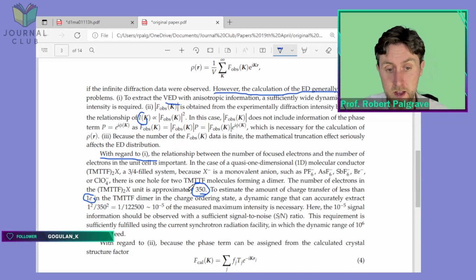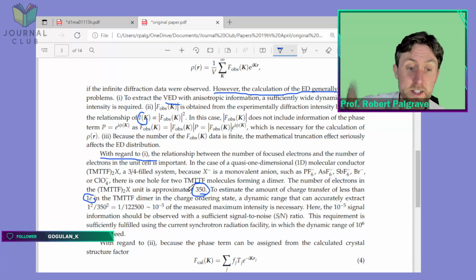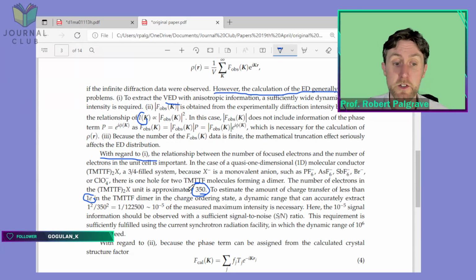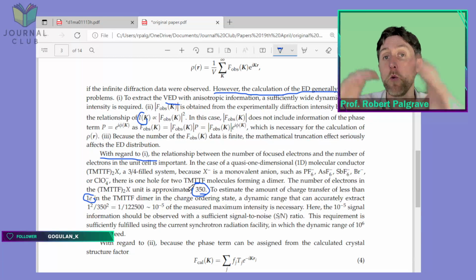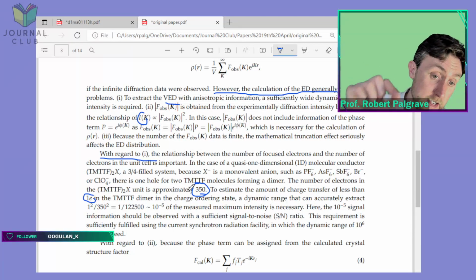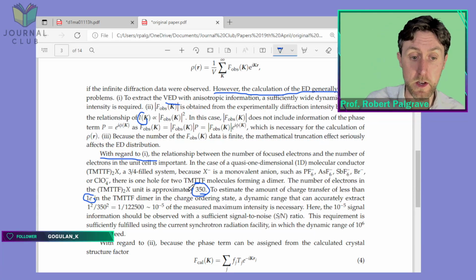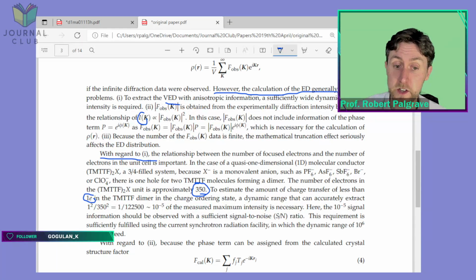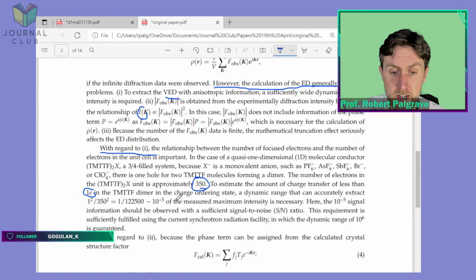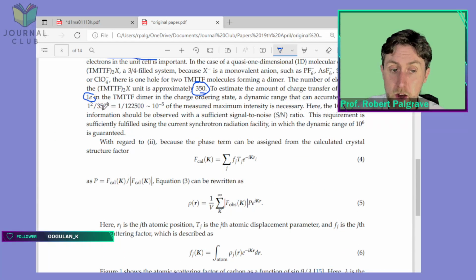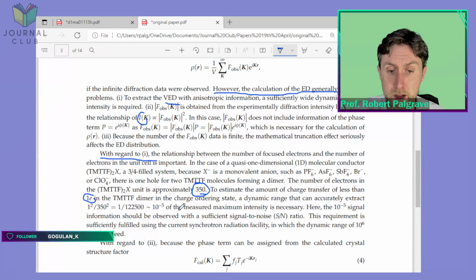So it's 350 electrons in total. One of those is what they call a focused electron, the electron that they are interested in for their particular problem. So it's not even all of the valence electrons. They want to see one particular valence electron in one particular part of this dimer, this molecule. So you're looking to see a change of one thing in 350 things. So the dynamic range that you need to accurately extract that is 1 squared divided by 350 squared, which is about 10 to the minus 5 of the maximum measured intensity.